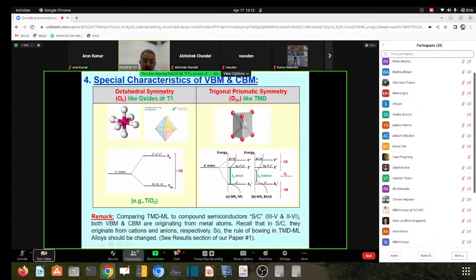Here, under the octahedral symmetry, Oh, like in the case of oxides, or the 1T phase that I mentioned, the third phase for the transition metal dichalcogenides, the metal is surrounded by six oxygen, like TiO2, for example, in the rutile structure. The titanium is under octahedral symmetry. It is the material that I studied in my PhD, but it's irrelevant for this talk. So these states split into two groups, Eg and T2g. T2g contains three states, xy, yz, zx, and Eg contains two states, z square and x square minus y square.